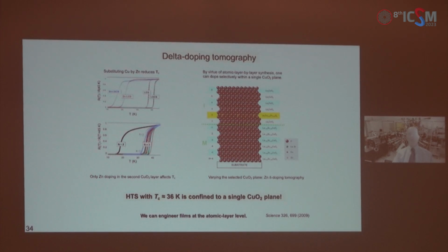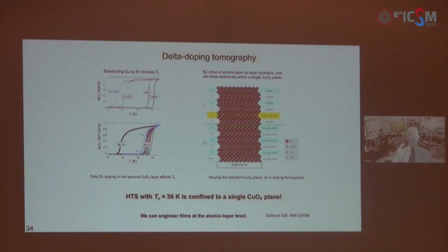We invented a neat new trick that we call zinc delta doping tomography, by which we were able to determine where this interface superconductivity resides. Zinc is known to be a very efficient poison for superconductivity in cuprates, even at very low concentration. So we use zinc as an atomic marker, in the sense that we dope zinc in a single copper oxygen plane. That's what's called delta doping. And then we make a series of samples like this, and in each sample we dope a different copper oxygen layer, and that's the tomography aspect of it.